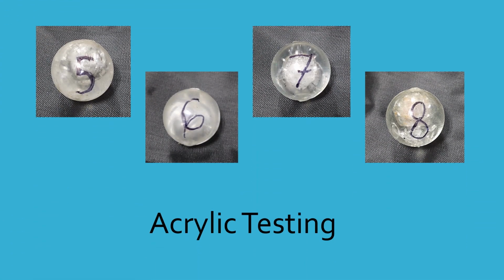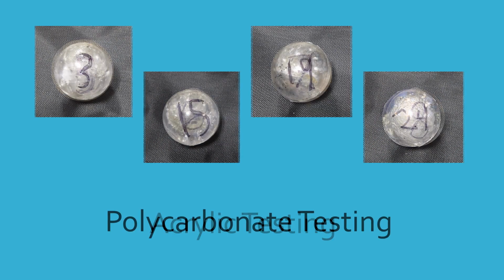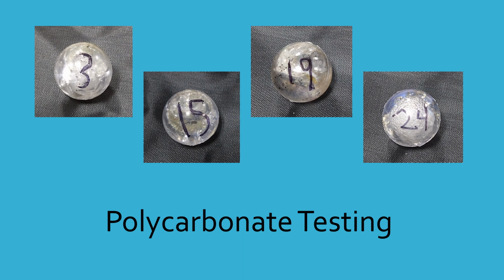Two materials were selected for testing. Acrylic was found to have an optimal mold temperature of 176 degrees Fahrenheit and an optimal material temperature of 518 degrees Fahrenheit, but was found to crack easily and produce voids. Polycarbonate was tested and found to have an optimal mold temperature of 225 degrees Fahrenheit and an optimal material temperature of 500 degrees Fahrenheit. Polycarbonate was found to have less cracking because it was a stronger material, but still had voids.